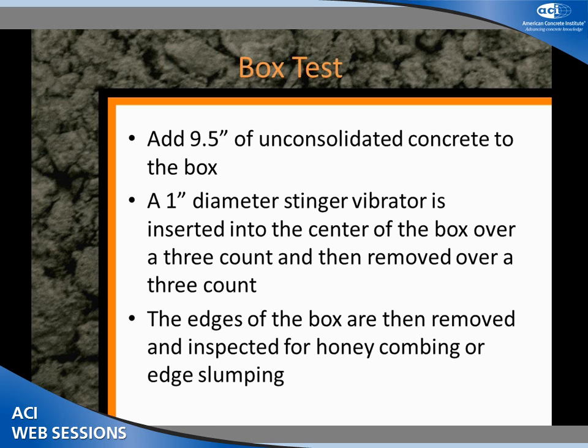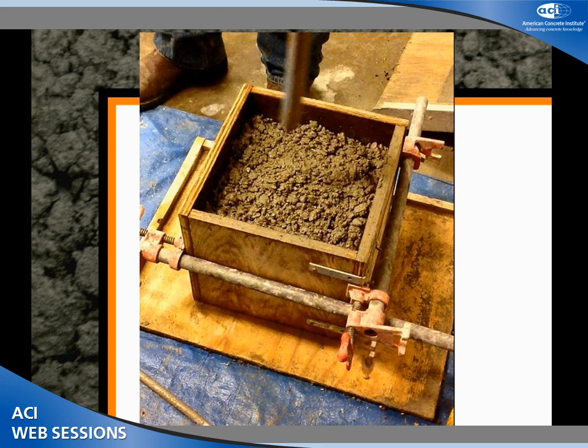We take a one-inch diameter vibrator — not a paving vibrator, this is a stinger vibrator like a bridge deck vibrator. We turn it on, count to three as we go down, count to three as we come out, and try to consolidate the concrete. Then we immediately drop those pipe clamps off, pull the edges of the box down, and look: did it fall over? Is there any honeycombing? What's going on?